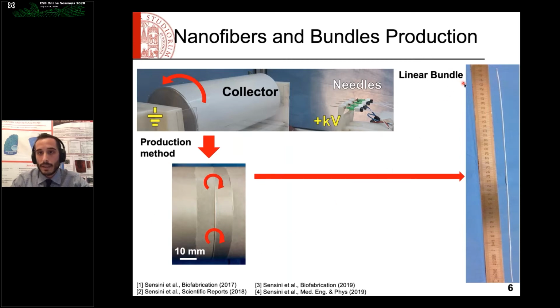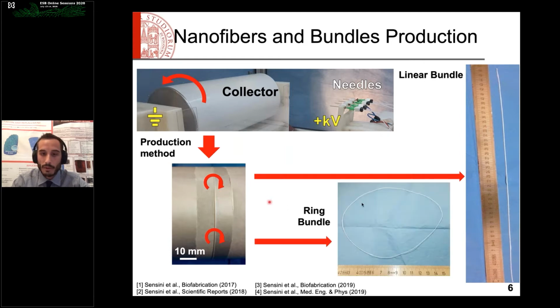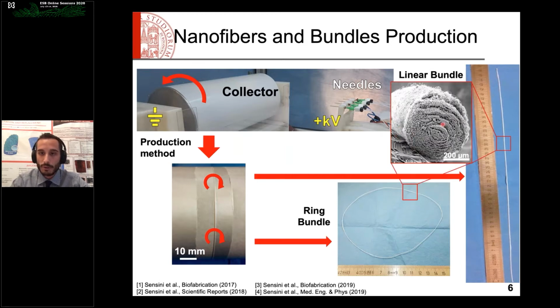By cutting them from the drum, I can obtain linear bundles of axially aligned nanofibers, or by pulling them out from the drum, we can obtain ring-shaped bundles of axially aligned nanofibers. From this SEM image, you can see how porous the structures are inside and how the nanofibers actually align with the structure.